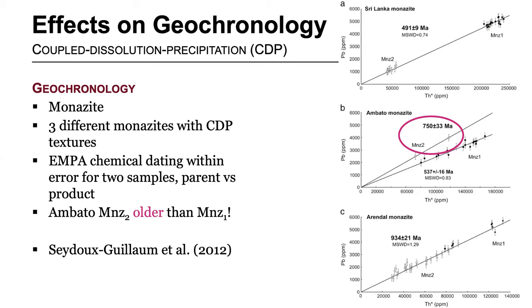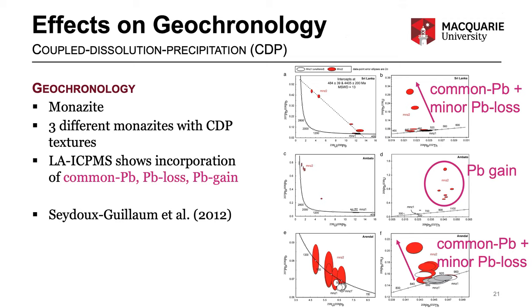They dated the samples with electron microprobe chemical dating and found the secondary monazite was generally younger than the primary monazite, which is a good start, but not with a very tidy age range. In the middle sample, they found that the age of the secondary monazite was actually older than the precursor monazite, which is an obvious problem. The same samples were also dated by laser ablation methods, and we can see some of the same patterns that we saw in our experiments: incorporation of common lead, some evidence of lead loss, but also some evidence of lead gain in the middle sample.